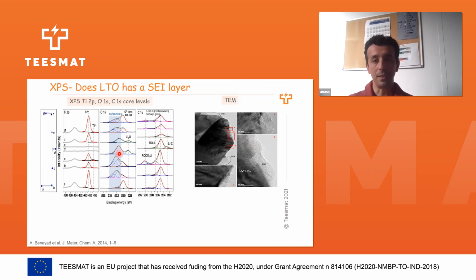So the XPS can finally give some order of magnitude of the thickness of the SEI. The good thing here is that XPS is a non-destructive technique, and we don't need to prepare the sample like in TEM. In TEM, we have to make a thin film and we have to wash the sample. That needs advanced preparation, which is not the case in XPS.